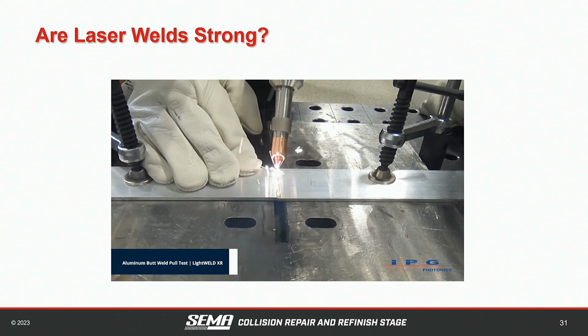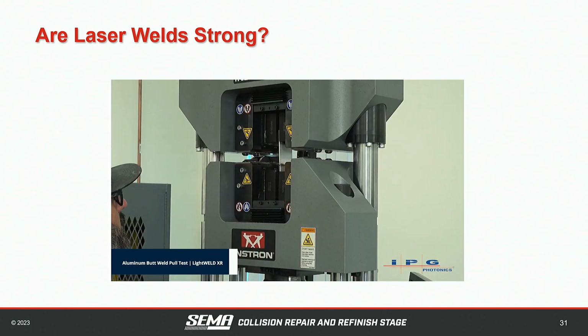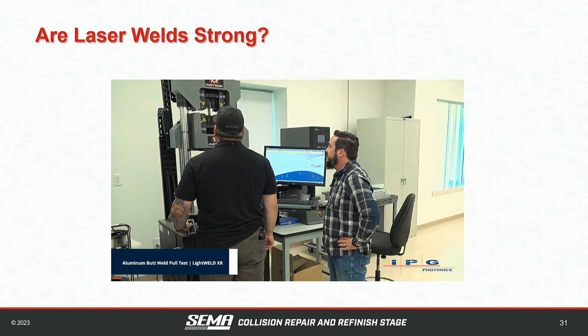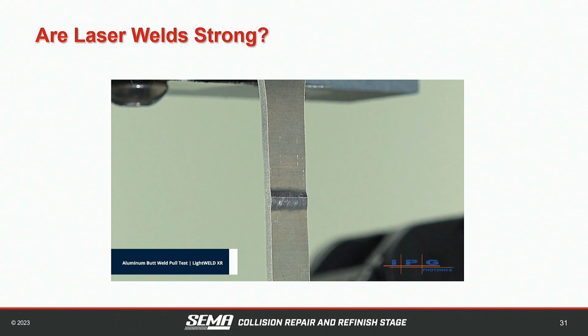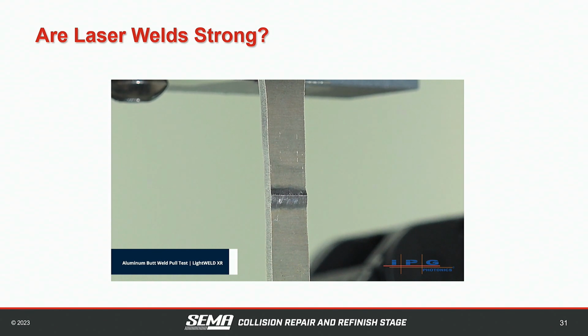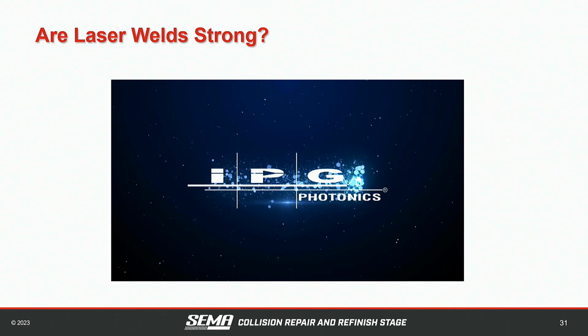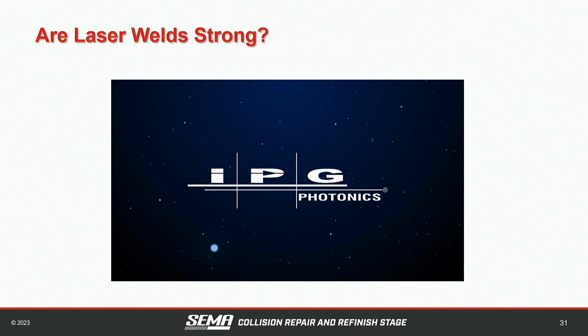So this is an aluminum welding test without wire, just autogenous. And they're breaking it. Notice how far away from the weld that panel broke. Almost every time we do that when we MIG or TIG weld something, it's going to break in the heat effect zone right next to the weld. This broke right in the middle of the panel. So that tells me the heat effect zone was so minimal that it didn't even affect metallurgically where that panel was going to come apart. That is very different than what we see with any other type of welding.